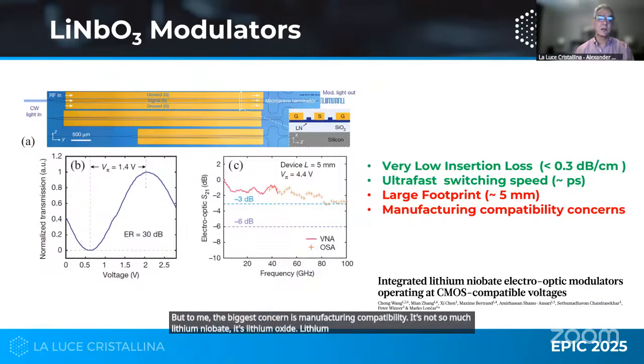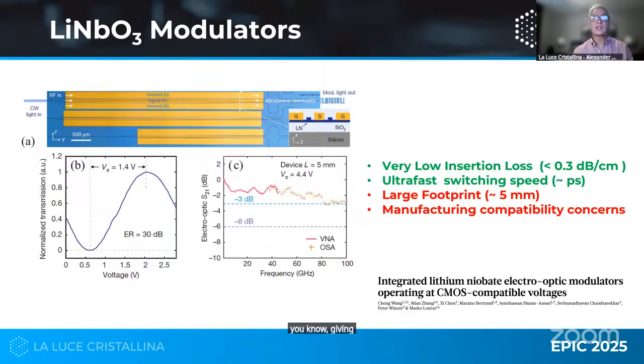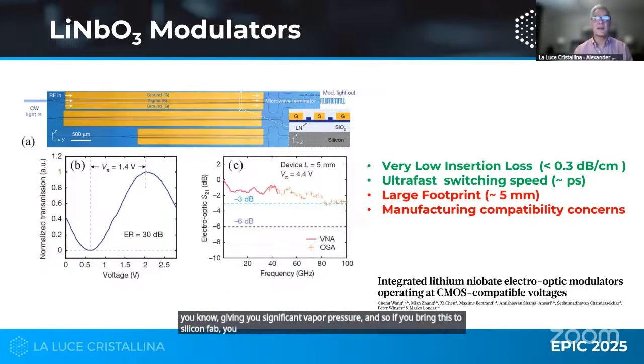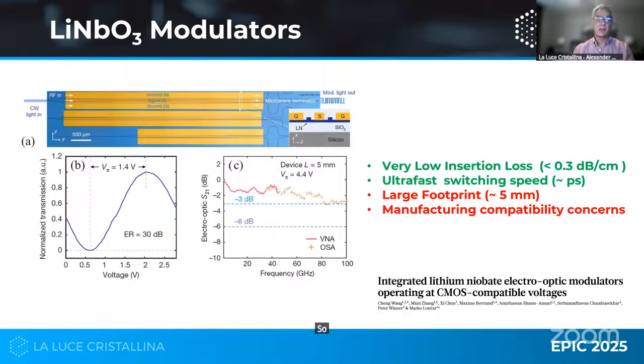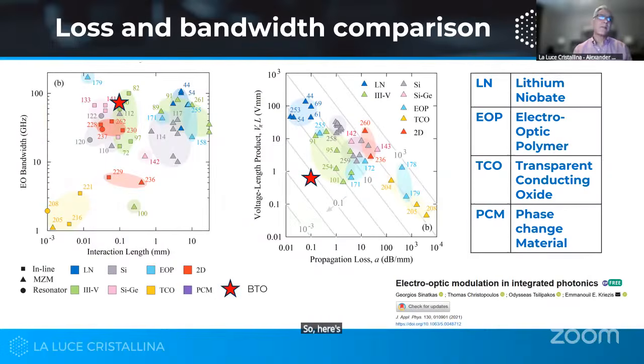Lithium oxide is extremely volatile. At room temperature, it's giving you significant vapor pressure. And so if you bring this to a silicon fab, you contaminate everything, and lithium is a known contaminant in the silicon process. So it is a concern. You have to build an entirely separate infrastructure. So here's some comparison in terms of, let's say, bandwidth and the size of the devices, and it's in this slide.